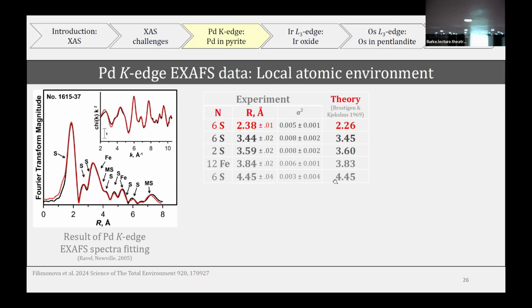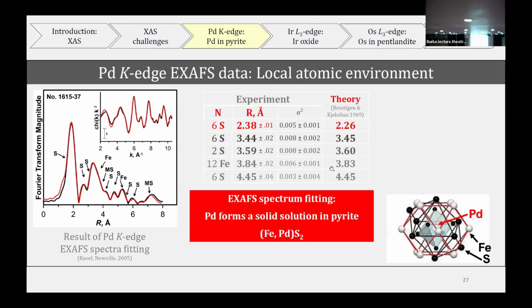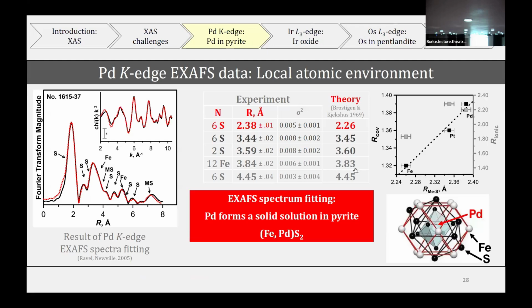So it's not a distortion; the expansion disappeared already in the second coordination shell. So here we've shown that palladium forms a solid solution. The kind of amazing thing here, for me, maybe not for everybody, is that we studied platinum before, the same work, the state of platinum in pyrite, and we noticed that there is a dependence between the covalent radii of the atom and the interatomic metal-sulfur distance for iron, platinum, palladium. Iron is a major component.